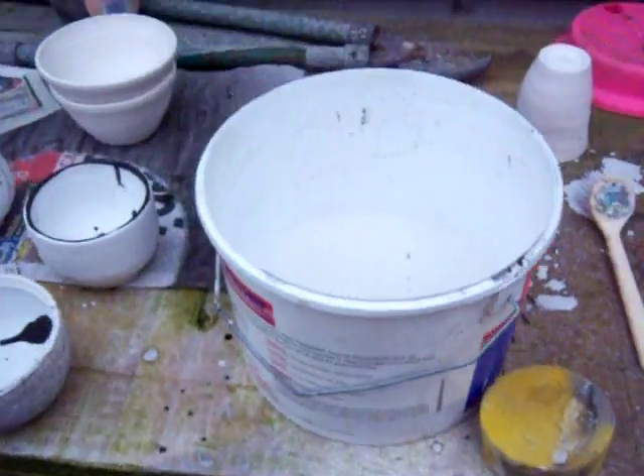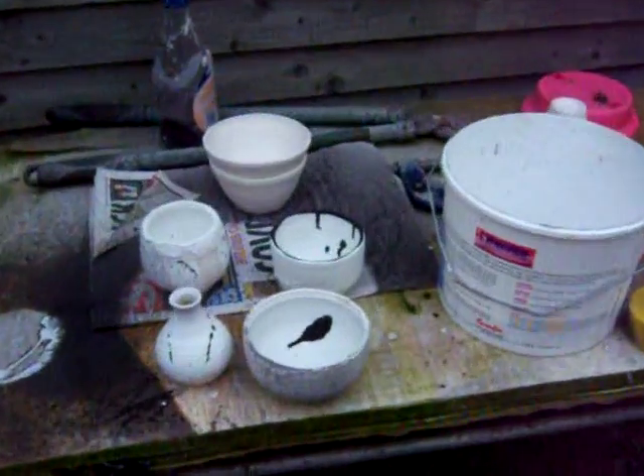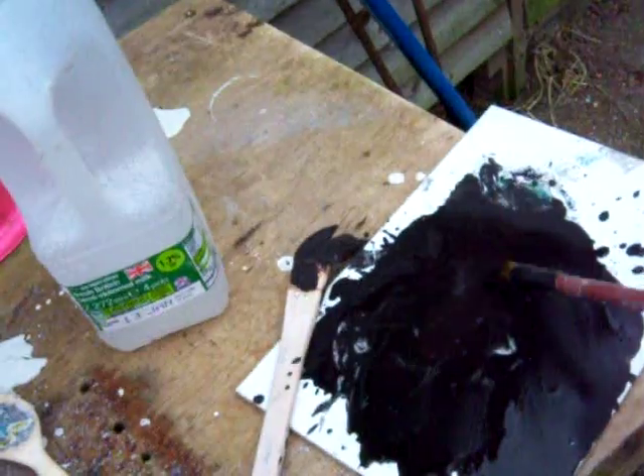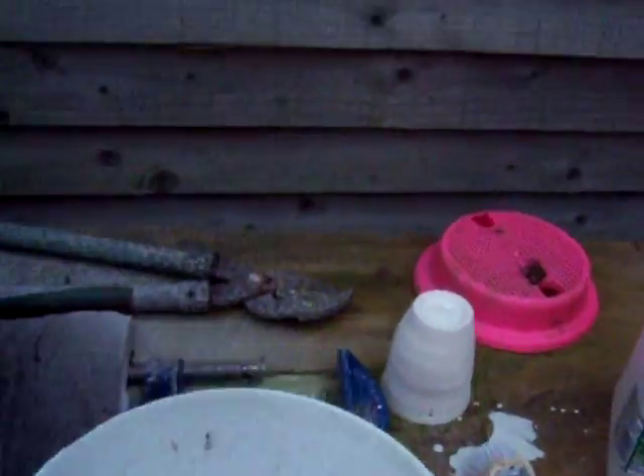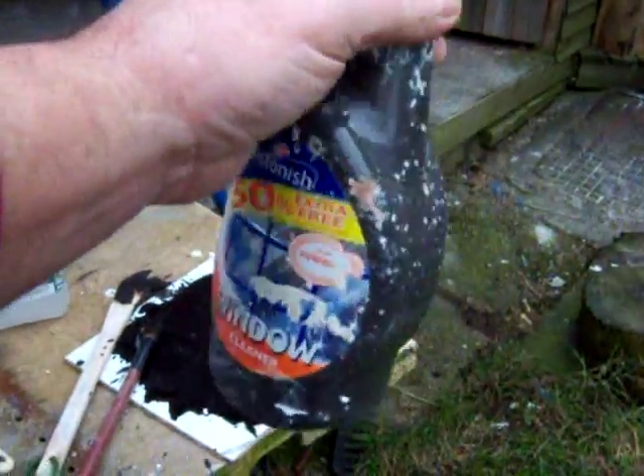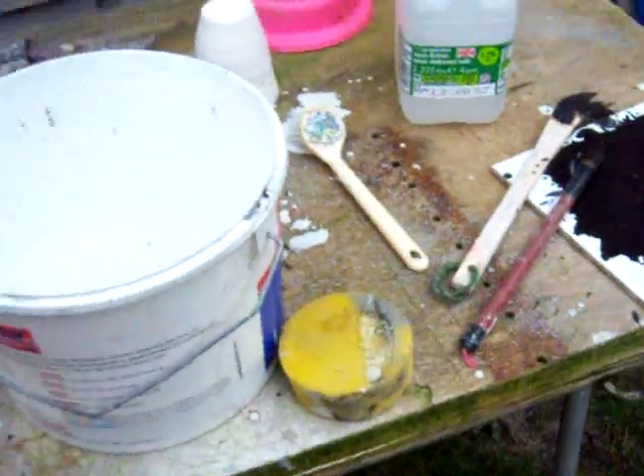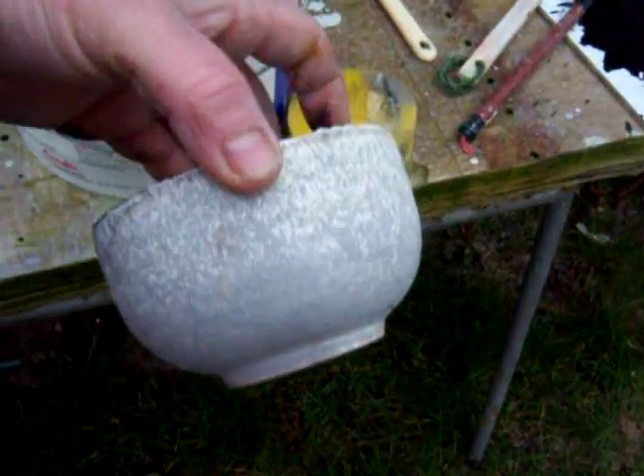I'll just show you one or two things I'm just glazing up now. This is my wonderful outdoor al fresco glazing table. Just a few pieces here waiting to go in. This is the copper oxide I've been using to paint on. What I've done is I've mixed up about 90% copper oxide and 10% alkaline frit, and I've sprayed that on the bottom of some of these pots to see if I can get a copper mat. So it's a bit of an experiment today, but I'll do another video when I'm getting the stuff out of the kiln.